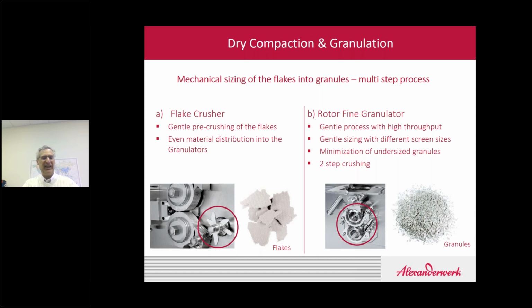So the material will exit out from the counter-rotating rolls in what we call flakes. Those flakes are gently milled up at first by what's known as a flake crusher. It's basically a rotating set of knives or rotating set of fingers that rotate very slowly, about 50 RPM roughly.